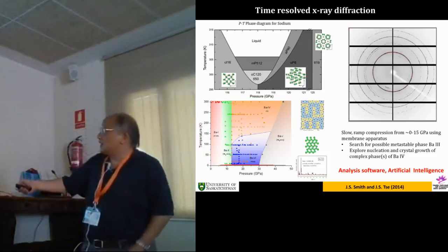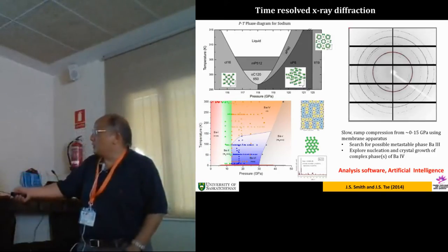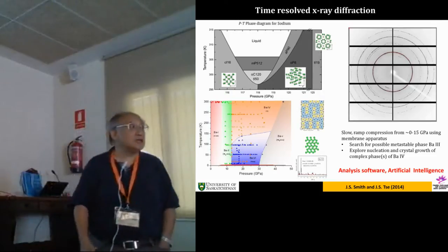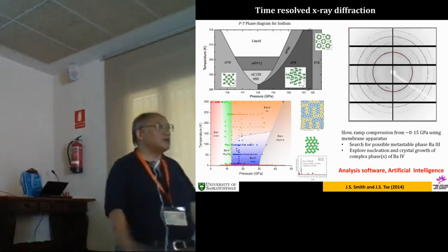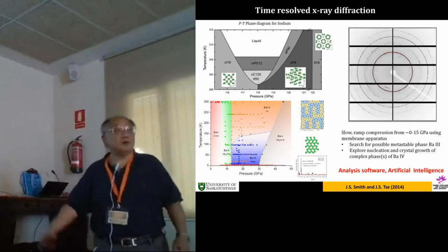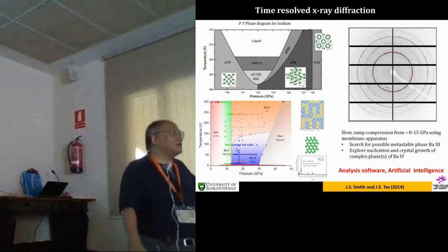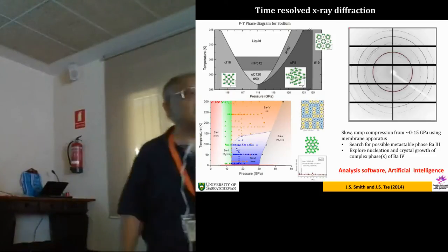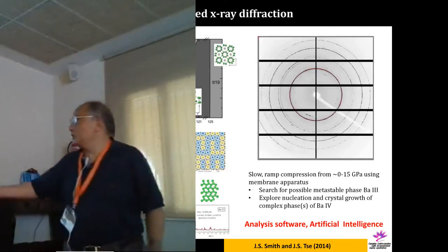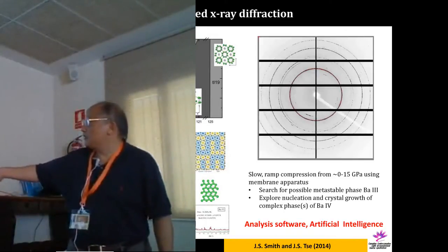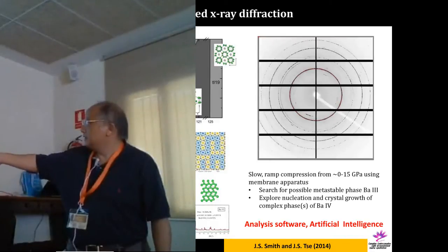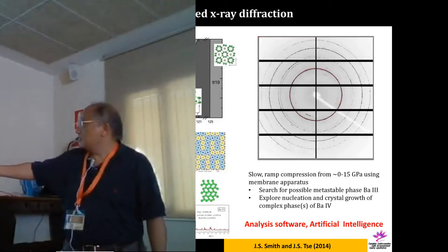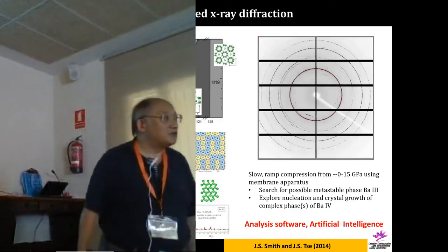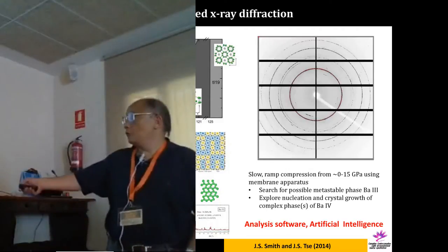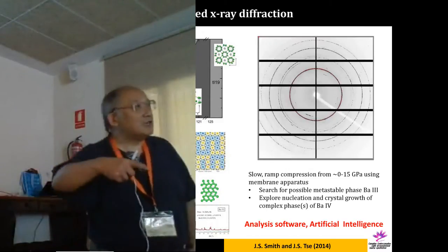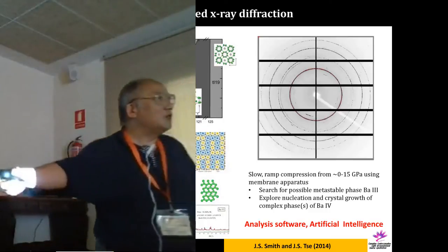Barium has a very similar phase diagram. And one thing, when we cool the barium to low temperature, it doesn't go to the complex Ba-IV structure. It actually is a very simple orthorhombic structure. So again, it's telling you kinetics is very important in high pressure. You just have to cool it down, and you can see the transition to Ba-IV, the complicated structure, around 100 Kelvin. So liquid nitrogen already changed the structure if you compress it cold. So really the kinetic or activation barrier from one structure to another is very low.